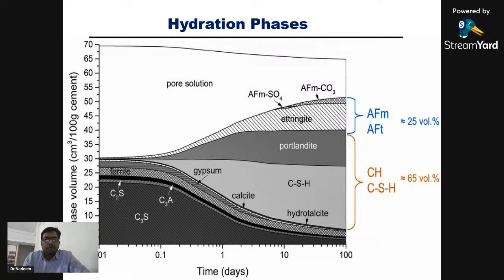This is another way of looking at that reaction. On the x-axis is time, and these are the four major compounds. Once you add the water, slowly you see the changes happening with respect to time. Now the majority of the compound is tricalcium silicate. Slowly and slowly it gets converted after some time. This is 100 days. The majority of the material is converted into CSH gel, portlandite meaning calcium hydroxide, ettringite, and other compounds. So CSH is in the range of 65%, and 25% are ettringite and aluminum ferrosilicates.